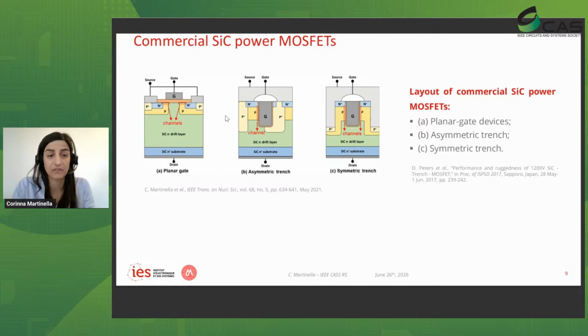We are talking about vertical power components. So we have our gate on top, the channel is formed in the P well, and the drain is at the bottom. Generally, we have an epitaxial layer, for example, for a device of 1200 volts, which is 10 micrometers in thickness. And then we have a substrate, which is hundreds of micrometers. So we have this planar design. Otherwise, we can have an asymmetric trench device, which is chosen as a design by some manufacturers. And then we have a symmetric trench design. In this case, the channel is vertical. Here we have a single channel, and here we have two channels.